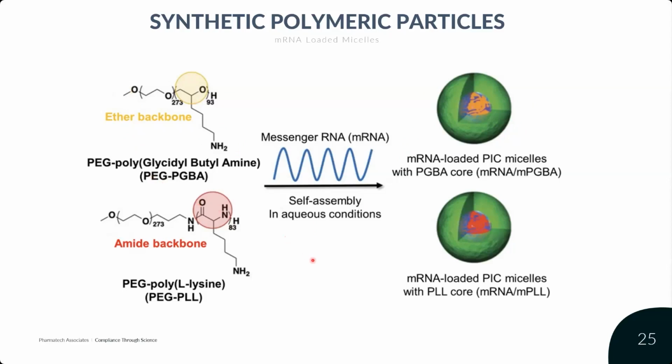And one additional advantage is that these polymers are all biodegradable. So as they degrade, they release the mRNA therapeutic payload. And then since they're thermodynamically limited to a certain size, one other advantage is that you're going to be able to not only get low polydispersity, but you get consistent loading of mRNA, because really it's almost like a stoichiometric conjugation.